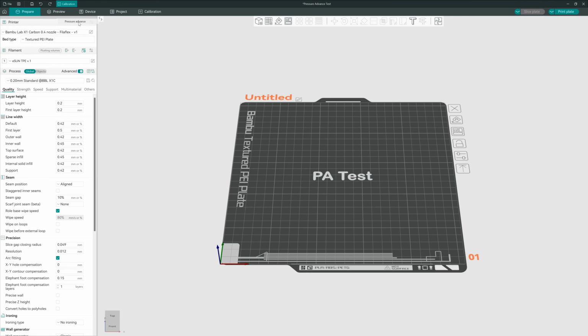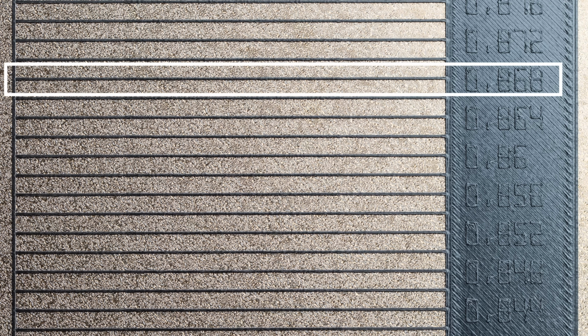To refine the accuracy, I run a second test with a smaller range. This time I set the minimum to 0.8, the maximum to 0.9, and set the step size to 0.001. Examining the second print, I found it difficult to spot major differences between the lines. In the end, I settled on 0.868 as it appeared the most consistent.